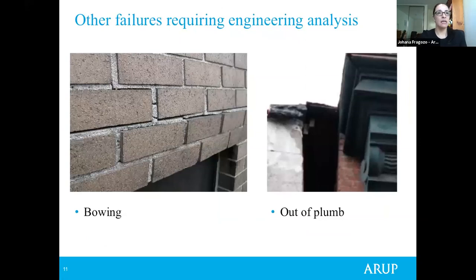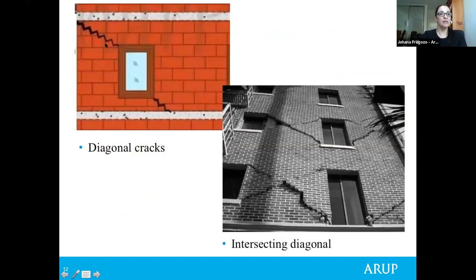Other types of failures in masonry walls: we have bowing and out of plumb, which are usually caused by movement of the building structure due to structural weaknesses. We have diagonal cracks. These diagonal cracks usually originate on one side of openings or across the spandrels, and could be caused by lateral displacement, heavier loaded areas that tend to move outwards, and it could occur soon after erection. Other causes could be deflection of lintels.